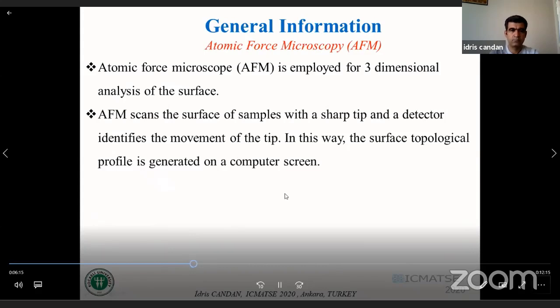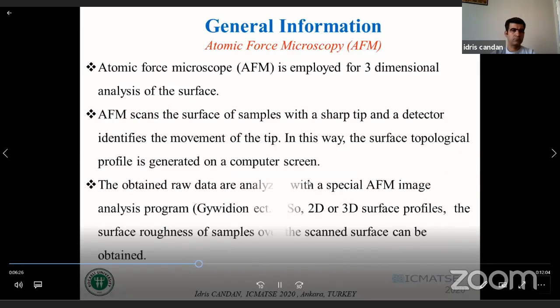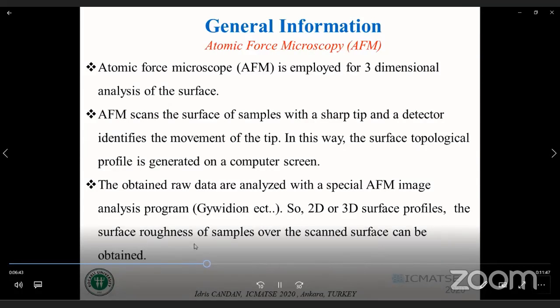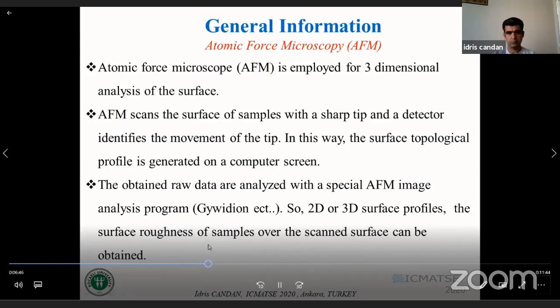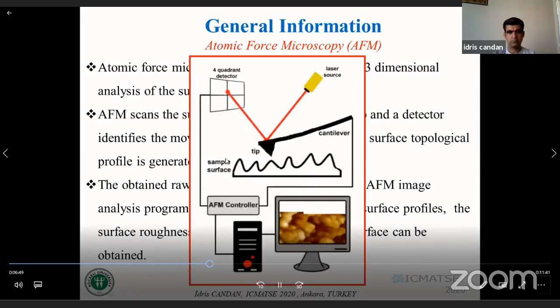AFM scans the surface of samples with a sharp tip, and a detector identifies the movement of the tip. In this way, the surface topological profile is generated on the computer screen. The obtained raw data are analyzed with a special AFM image analysis program like Gwyddion, and so 2D or 3D surface profiles and the surface roughness of samples over the scanned area can be obtained. And here you can see the schematic illustration of the atomic force microscopy.